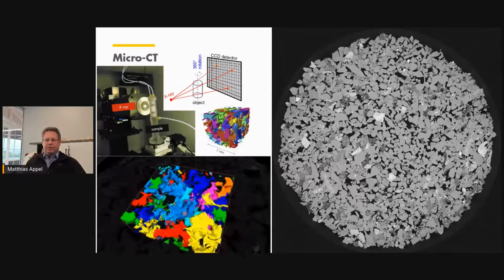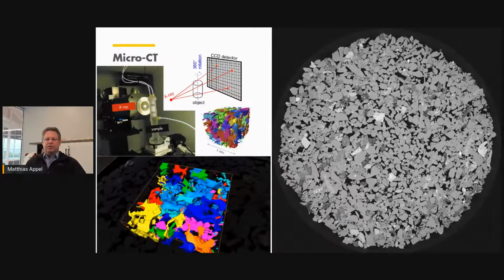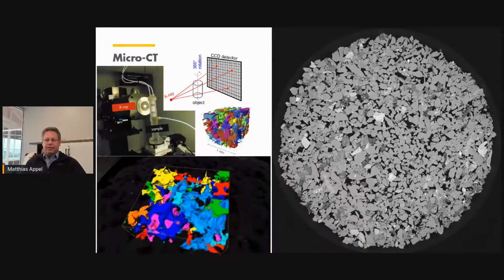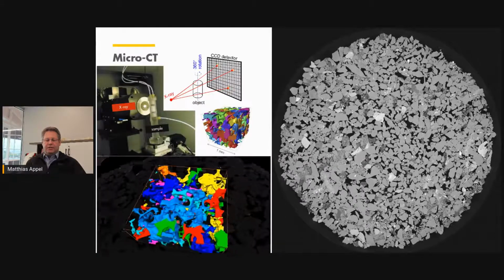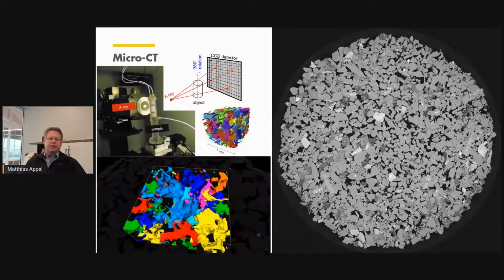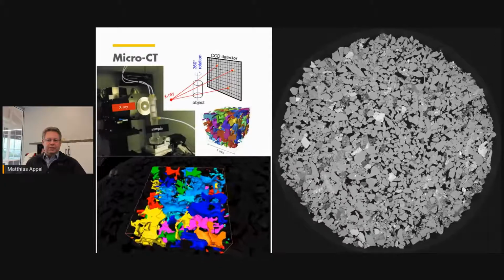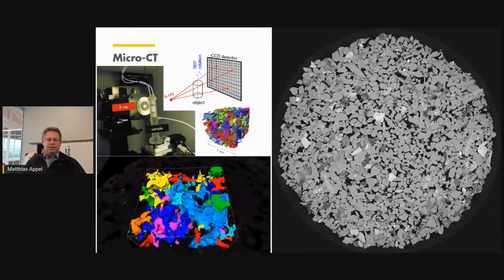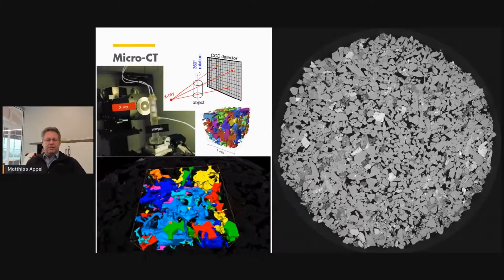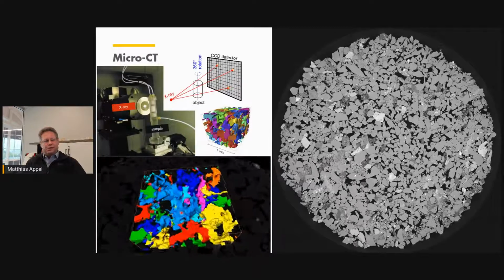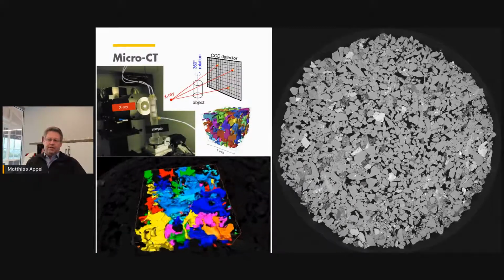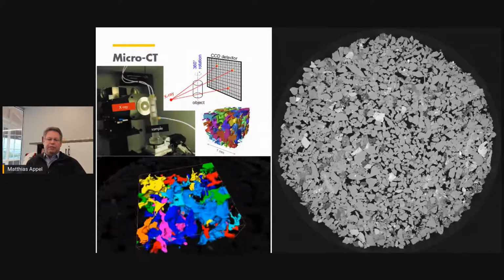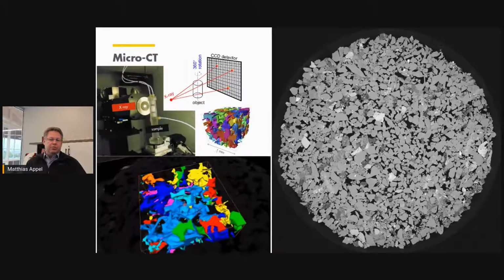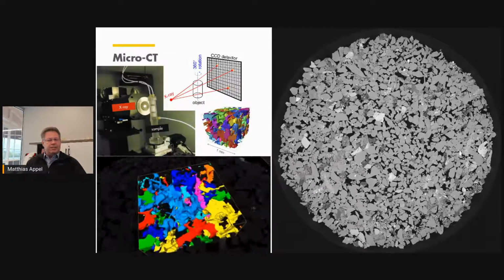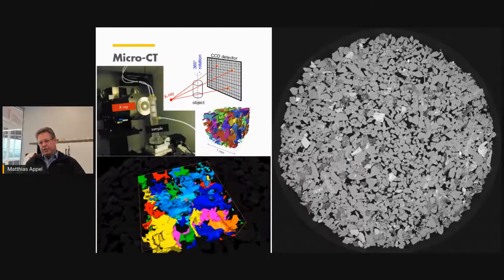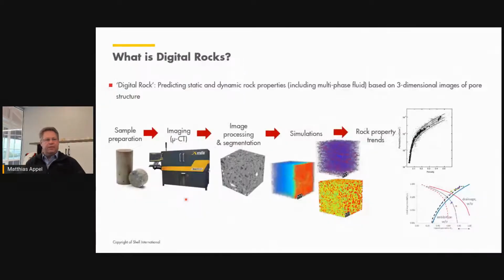That's what's rotating here on the bottom left. Each color represents a cluster of connected pores. And that cluster of connected pores, of course, is related to the resolution of the image. So you need to say that that pore cluster is connected for the given resolution of about 1 micrometer. It might be connected at a lower resolution, but we don't see that. But that's important for the application of digital rock, which I quickly want to introduce here.